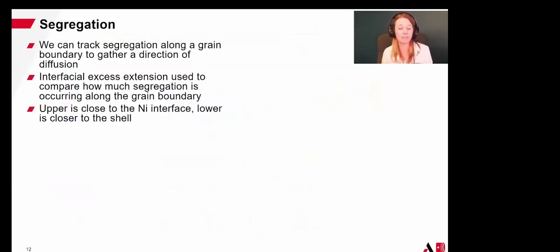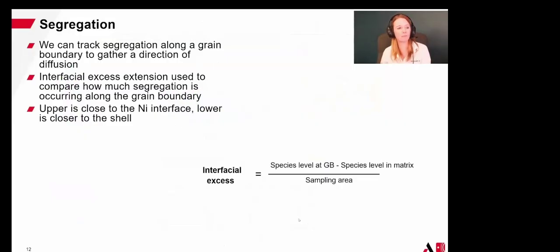But if we look at these grain boundaries, one of the things that we can do is look at what is segregating to those grain boundaries. And we can do this in a couple of different ways, but one of the standard ways in Atom Probe is to look at the interfacial excess, and that's going to give us a normalized amount of segregation at the grain boundary. So the way that this is calculated is we're going to measure the species level, so whatever species we're interested in, at the grain boundary, and subtract that species level at the matrix. So this is the amount over and above what is in the matrix. And then we're going to divide that by the sampling area to have an area normalized measurement of segregation.